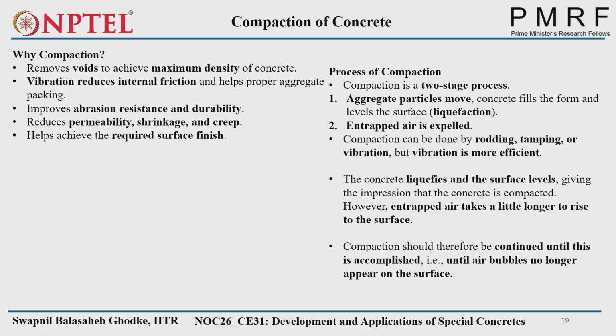But compaction is considered a two-stage process. One is aggregate particle movement. When you are going with concrete compaction, first of all, concrete fills the form and levels the surface with the help of liquefaction. Suppose you are using a concrete poker and going with the vibration. Initially, the workability and slump will improve, and that will level the concrete surface. But the voids available in the concrete will take a little more time to expel from the concrete matrix. So that's why we have to be careful about the timing of the compaction.